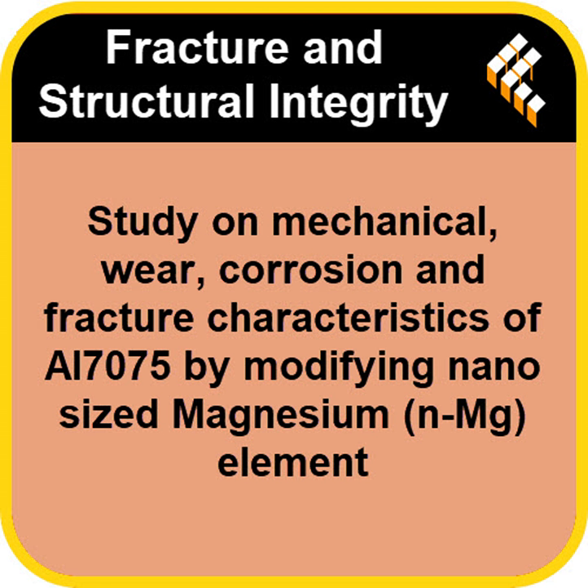A 35% reduction in the material's ability to absorb shock. That's not a compromise, that's a structural casualty. It really is. And the very mechanism that delivered that 9% tensile gain is what caused this 35% toughness loss: those rigid, brittle intermetallic compounds. The ones that were so good at blocking deformation. Exactly. They also make the alloy much more prone to sudden catastrophic fracture under a dynamic load. You've basically traded elasticity for pure stiffness. That major drop in toughness is worrisome for any component that has to withstand vibration or sudden impacts.